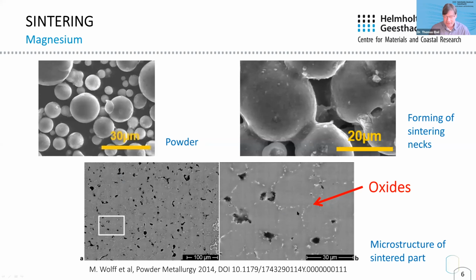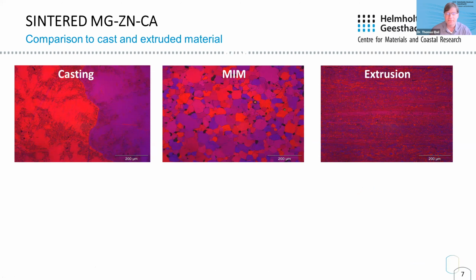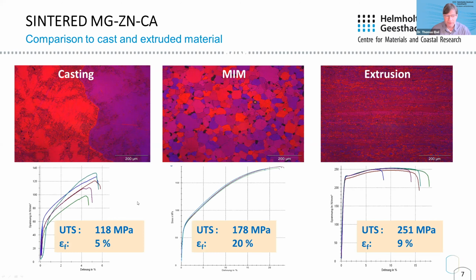So you could say oxides, that's very bad, but they have at least one benefit, and this is visible in this picture. This is the same alloy processed by casting, by sintering, so metal injection molding in this case, and extrusion. You see the big difference in grain size. The nice thing is that these oxides hinder grain growth very strongly. So in principle, you get the grain size of the powder particles. When you use finer powder particles, you can get a finer grain size. Not as fine as in the extruded case, of course, but at least much better than casting. And you can see this in the mechanical properties in a comparison.